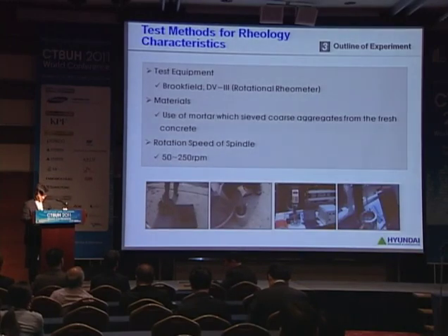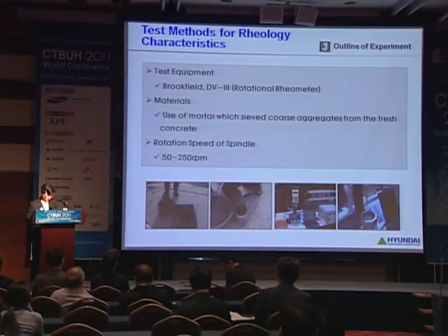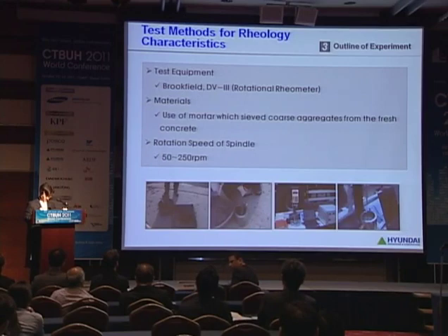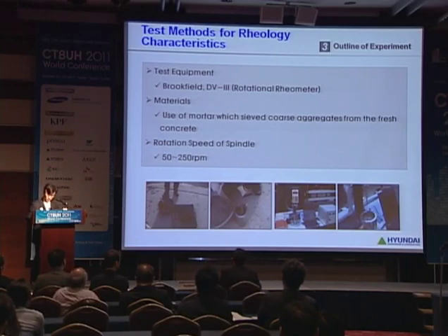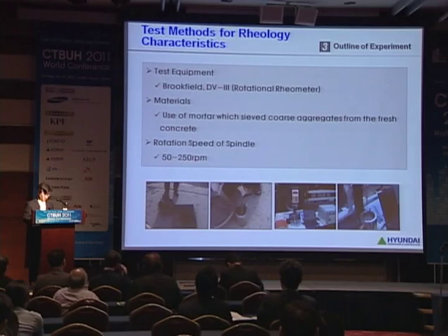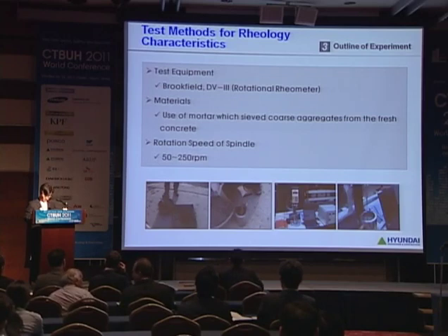Next, test methods for rheology. The Brookfield Company's DV3 rheometer was used in the rheology test. Shear stress and shear strain rate were calculated from the torque of the spindle, which was measured by gradually increasing the spindle rotational speed in a sequence of 50, 100, 200, and 250 RPM, and then decreasing. The mortar used in the test was taken from the concrete before and after pumping by extracting coarse aggregate by sieving.